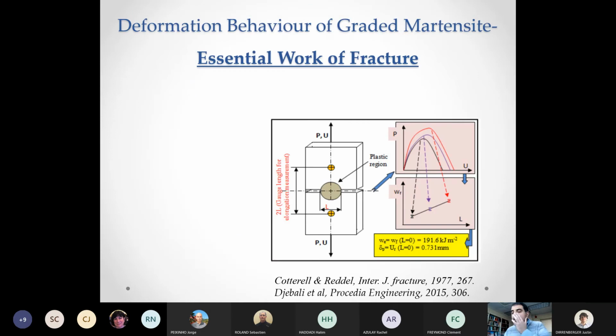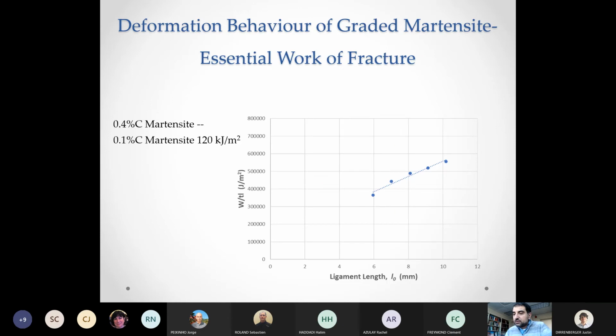The other test we did to kind of assess the toughness of these materials was to look at the essential work of fracture. So it's a useful test when we have thin sheets that are in plane stress conditions, and it gives an idea of the amount of energy which is absorbed per meter squared of material as the crack tears through this double notch sample. So I plotted here the amount of work, the area under the force displacement curve, normalized by the ligament, the area of the ligament that the crack has to travel through. And the important point about this test is the intercept here gives us this essential work of fracture in units of joule per meter squared.